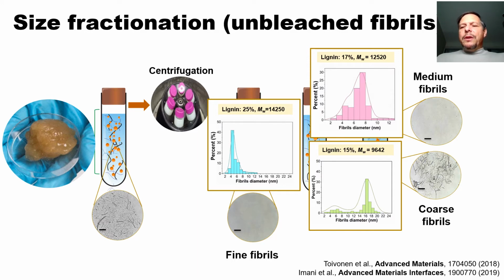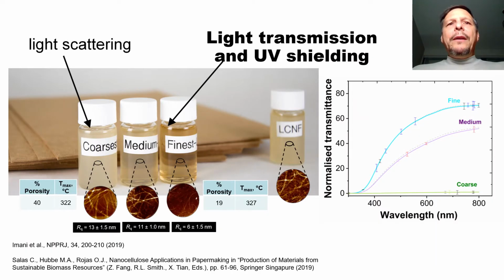And this is quite interesting because I think this is a fact that we can exploit for many different purposes, including coatings, and in this particular case, to manage light scattering. In fact, with these lignin-containing fibrils, we can produce very lightweight papers that will have completely different porosity. As you can see here, the ones on the left have a porosity of 40%. The ones on the far right, the finer ones, have much smaller porosity. And this is explained by the arrangement of the fibrils in space, as we discussed earlier. And the roughness of the papers will be quite different.